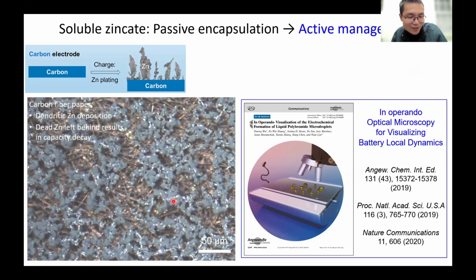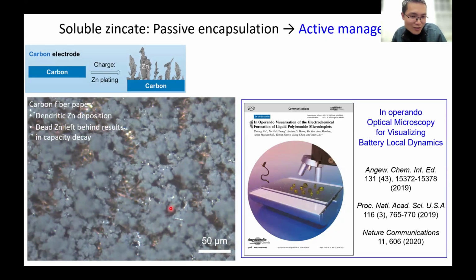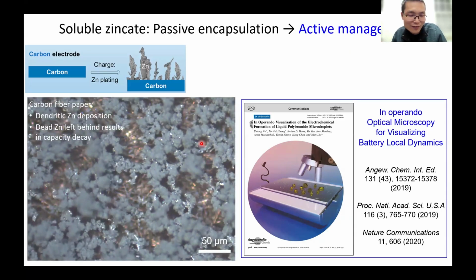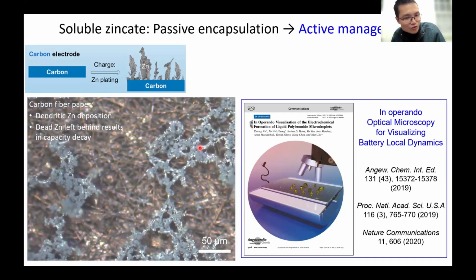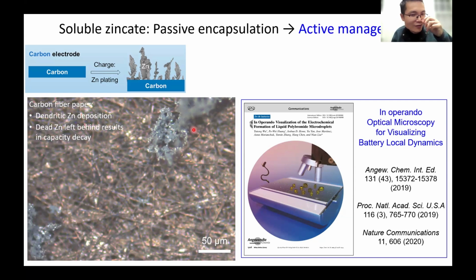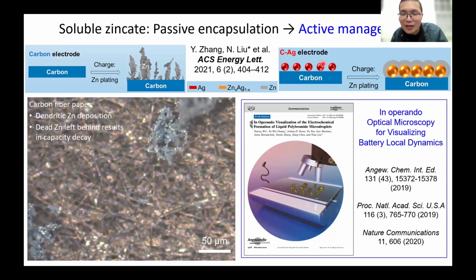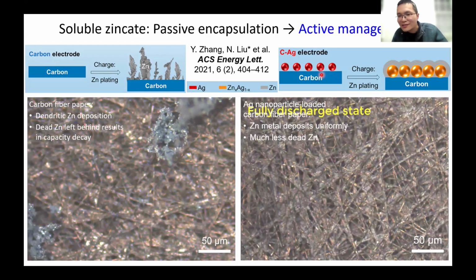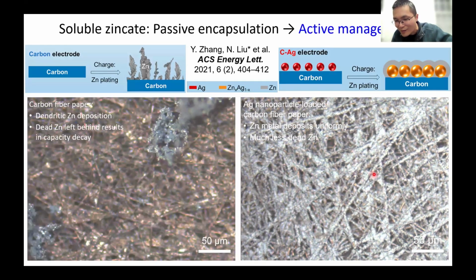So you can see this is zinc deposition on a carbon fiber paper electrode, and it forms this dendritic structure instead of a uniform flat film. Then when you switch the current to strip the zinc, it peels off and forms dead zinc, which causes the efficiency loss of the electrode. So what we did here is to spread a layer of silver nanoparticles on this carbon substrate. Silver can alloy with zinc, and we hope it can anchor where the zinc deposits and change the deposition behavior.